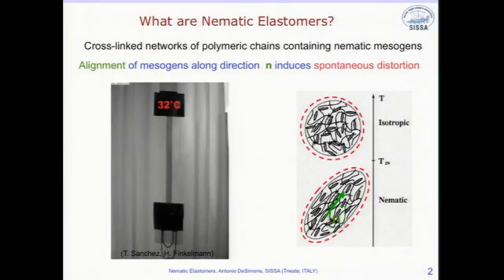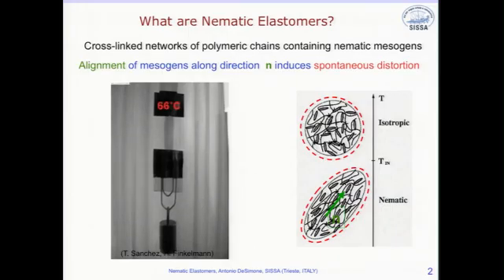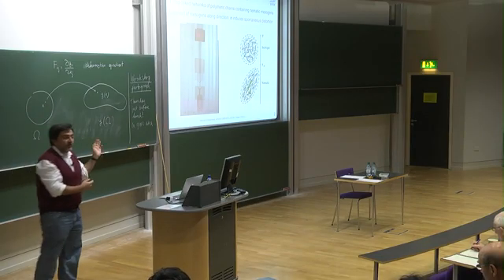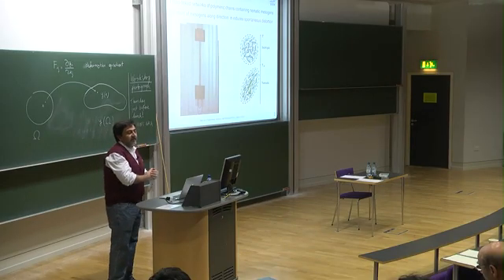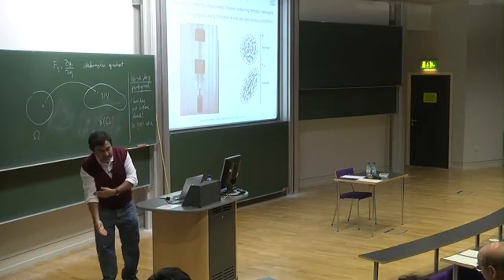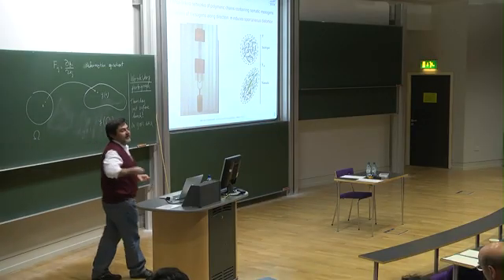So you will see a material that is being cycled. This is low temperature in the nematic state, heated up, it goes back to the isotropic state. And you see a huge change of length, of the order of 300%. And the cartoon on the right, the sphere that becomes an ellipsoid, is the conceptual rendering of this distortion that you see physically. Why is the weight being lifted? It's to show that it can perform work, but it would work in the same way even without it, maybe with some floppiness, because this is a ribbon. But it's just to show that it can lift the weight.